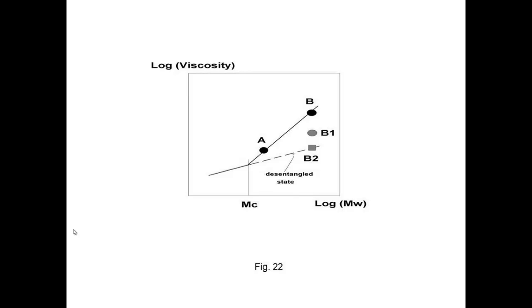First of all, therefore, I need to address the fact that is it possible to process such a state? How does it return to either B or B2? In what time? Is it following the kinetics dictated by the reptation model? And is the final state the B state, or can I have some processing conditions which bring B1 such that the final state, the return state, is B2? Or alternatively, is B1 stable? In other words, in this research we're concerned with the stability of entanglement states.